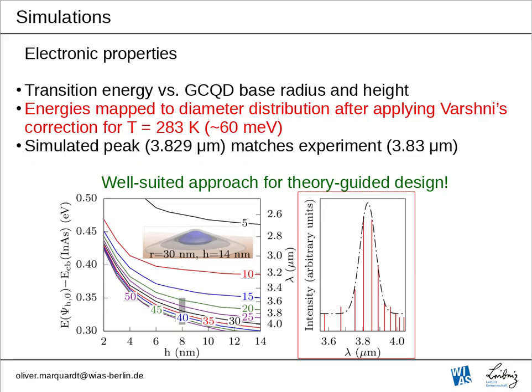And we were really surprised to see that the simulated peak is extremely close to the one observed in the experiment. That really surprised us, because we have essentially taken the formalism out of the box, plugged it into our software. We have taken the parameters from Vurgaftman just as they were without any modification, and then applied the Varshni correction on top of that. That's everything that entered, and still the agreement is extremely good, and we think it's a well-suited approach for theory-guided design. So of course we cannot tell experimentalists to grow extremely specific systems here with one very well-defined diameter or height, but we can point the direction what to do with their systems if they want to address a certain spectral window in the mid-infrared.